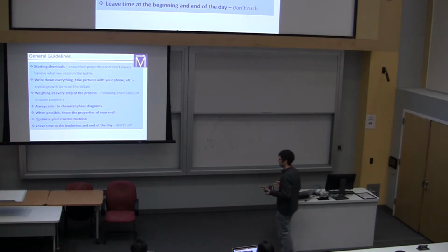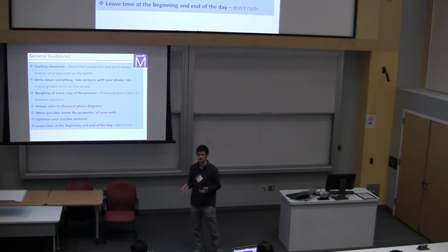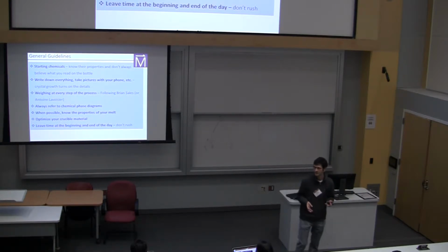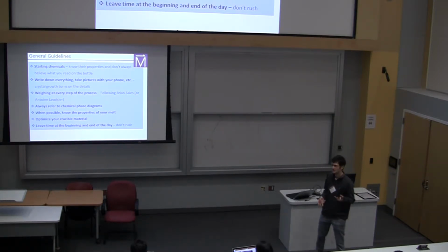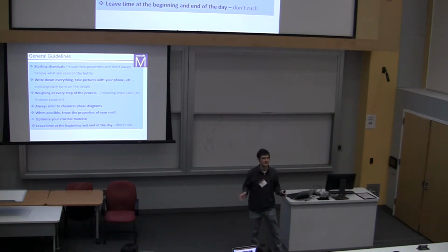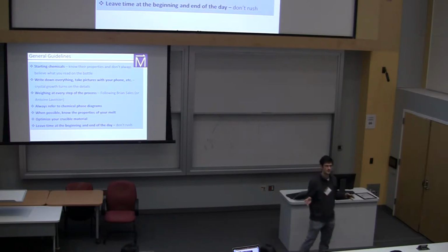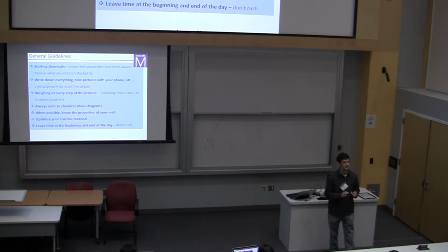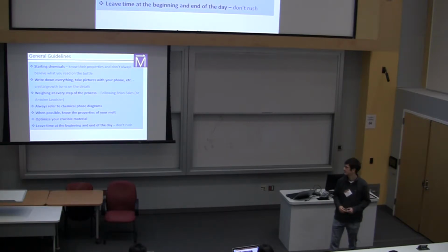Well, obviously you're going to know how much starting material you had, but it's useful then to mass the entire batch yield, right? If the batch yield gives a mass that agrees with the amount of the thing that you were trying to make, you can be pretty sure that you made what you intended to make. If it is some completely weird number, it's probably not what you were trying to make, right? Maybe the flux is actually now part of the crystal. Maybe if it was an indium flux, now you have some indium containing crystal, right? So this gives you a hint immediately with no work whatsoever, to know what you've grown. I think that's important to do.